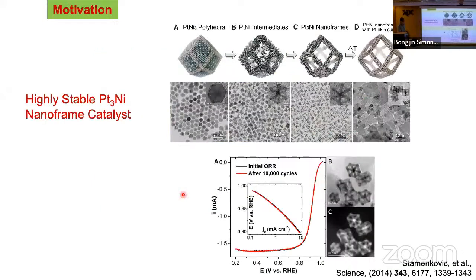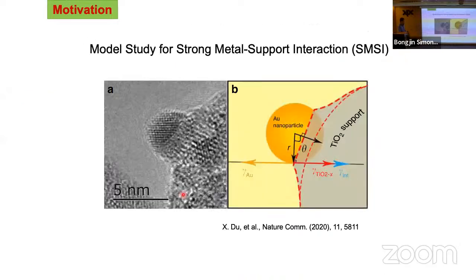In the meantime, Boya, who I work with together, came up with the so-called nanoframe catalyst. He developed a more nanoparticle engineering approach, and they were able to make this very special type of nanoframe which has platinum skins on the surface. And then he showed this is very stable over 10,000 cycles. So they were pushing it, but still, platinum-3 nickel is not really the winner of the catalyst at the moment. The platinum cobalt is still doing this, replacing the platinum nickel. Nonetheless, even platinum cobalt also suffers a little bit of this stability issue. So this is the clear motivation that I wanted to introduce.